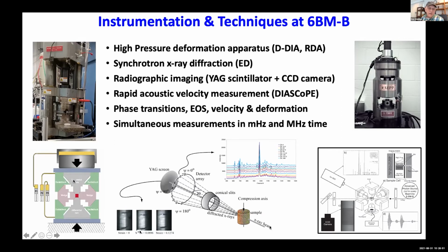This is a picture of the conical slit system, and around a cone there are two circular slits, and we have an array of detectors around the cone that each simultaneously creates a diffraction pattern as the X-rays are on. If you think in terms of monochromatic light, these would be like different slices of the cake when you cake the beam going around in the horizontal direction. So this provides input to the stress field and so forth. And each detector has a diffraction pattern.